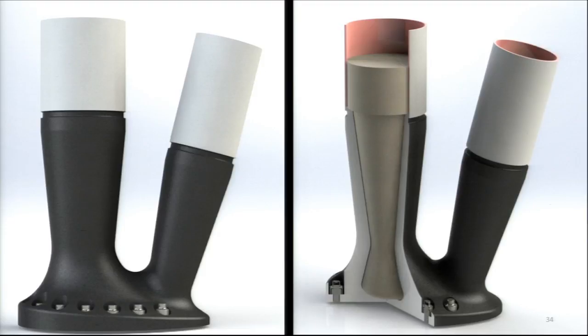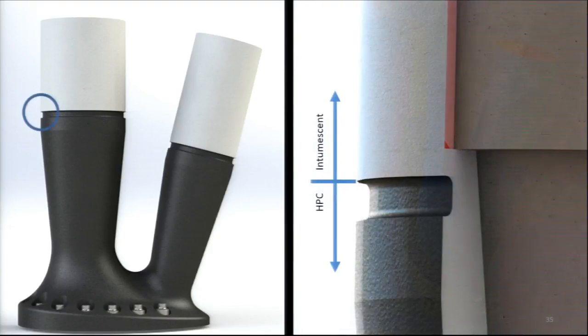So the columns above the cast node, which are hollow steel sections, are intumescent coated, and the intumescent coating actually ends at the cast node, and then the cast node is going to be coated in a different colored high-performance coating. To address the fire and blast resistance, we designed the casting so that it could be concrete filled. And so you see on the right a section cut through the casting showing that concrete filling. And here you can see just a close-up of that joint detail as to where the two types of coating systems are going to transition.